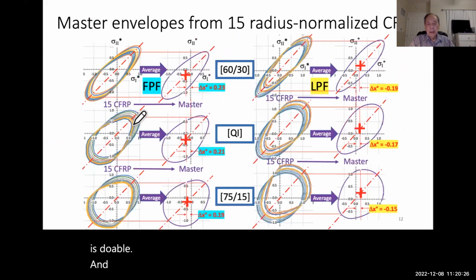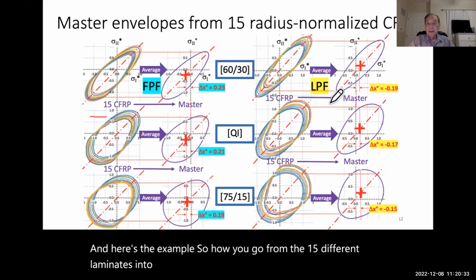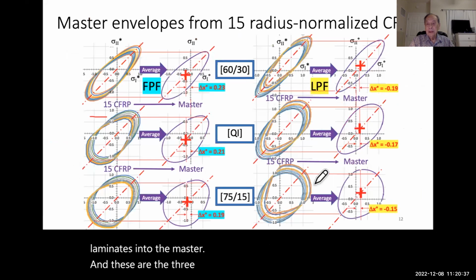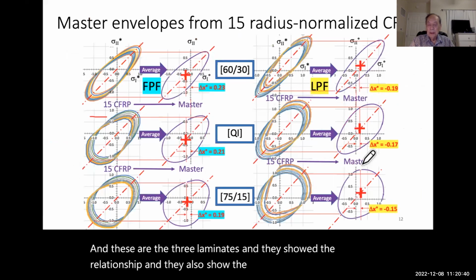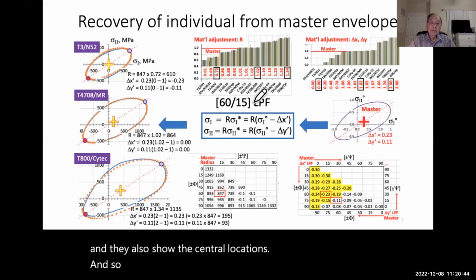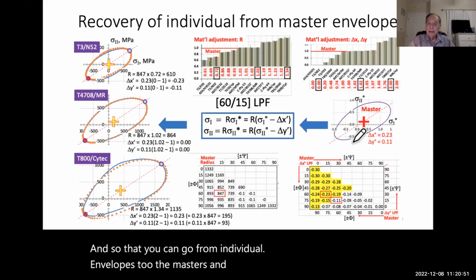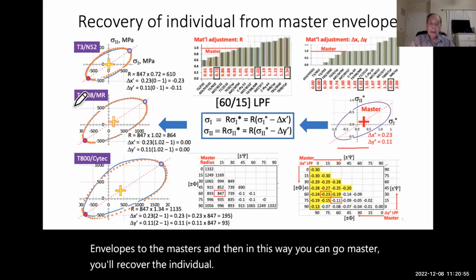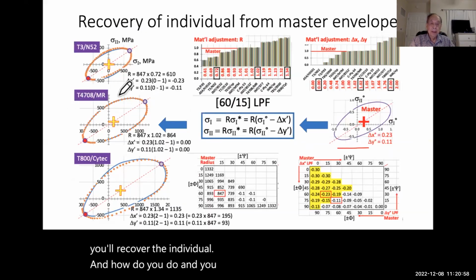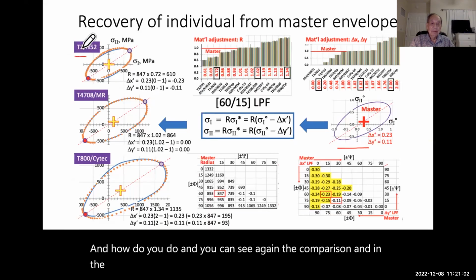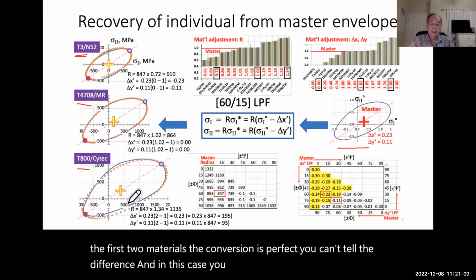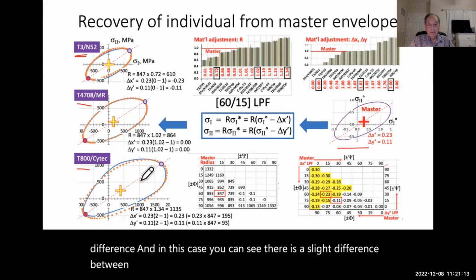And here are the examples of how you go from the 15 different laminates into the master, and these are the three laminates, and they show the relationship, and they also show the center locations. So you can go from individual envelopes to the masters, and in this way, from the master you recover the individual. And how well do you do? You can see again the comparison. In the first two materials, the conversion is perfect. You can't tell the difference. In this case, you can see there is a slight difference between the actual starting value versus the one that you recover.